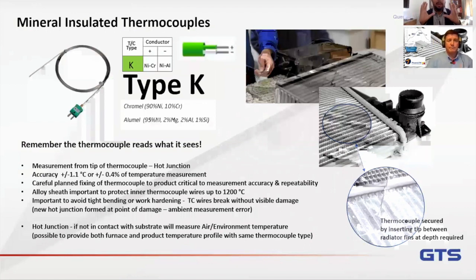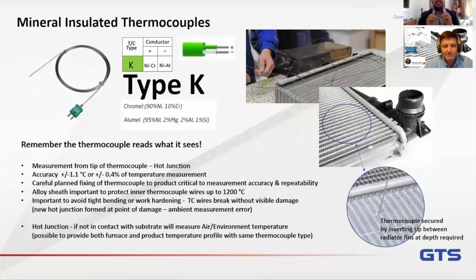So we've talked about the actual design or the engineering behind the thermal barrier, but going back to measurement, one thing that we need to have in mind, and it's very, very important, is the characteristics of the thermocouples. There are many varieties and constructions of thermocouples, but when we are dealing with atmosphere, probably the mineral insulated thermocouple is going to be your best option, right? It is. That's the thermocouple type we would normally recommend. Typically a type K thermocouple, which will give you the accuracy we're looking for if it's a special error thermocouple, typically 1.1 degrees Celsius or 0.4%, depending on the temperature you're reading.